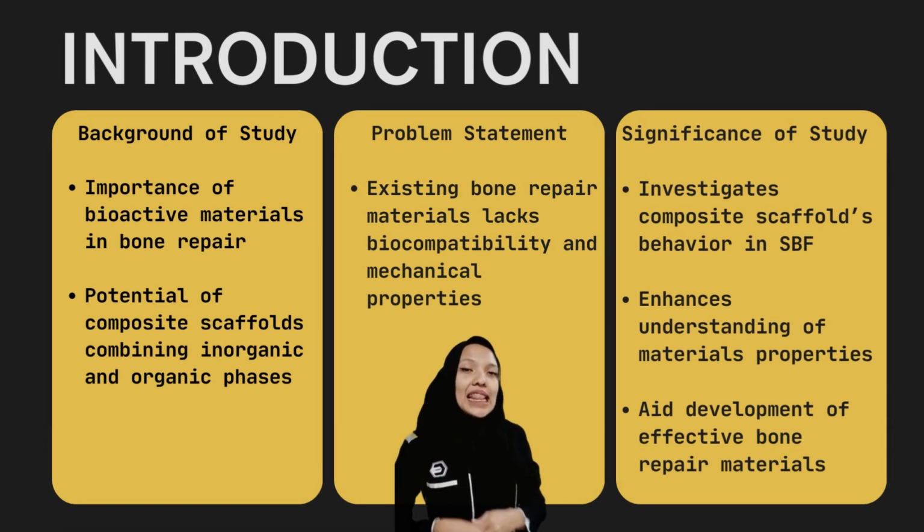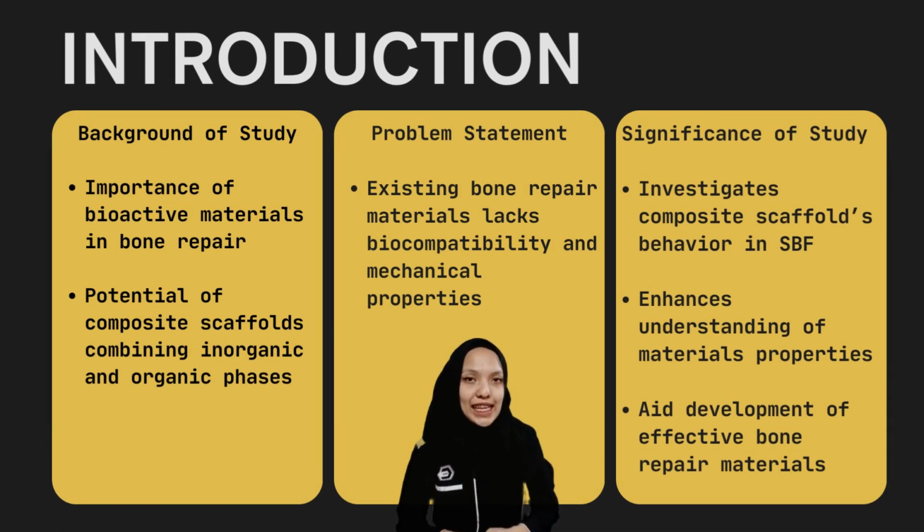To begin, let's delve into the background of the study. The importance of bioactive materials in bone repair has been well established as they can interact positively with biological environments. Despite the significant advancement, current bioactive materials for bone repair have limitations in their mechanical properties. For example, calcium silicate is highly brittle with a fast degradation rate that is faster than bone formation, hindering its commercial success.